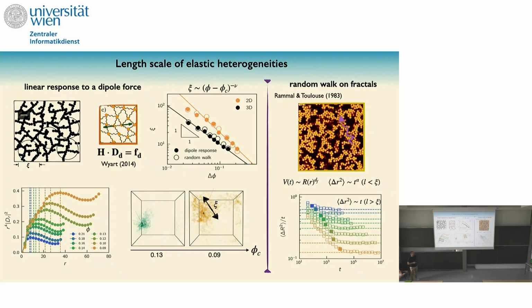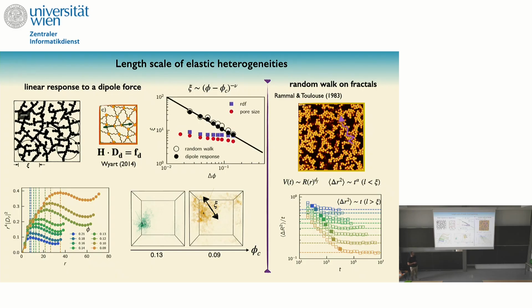Again, you might argue, and people have measured many other length scales, that maybe the important length scale is the size of the pores in my system. Maybe the important length scale is the one that comes from the radial distribution function when the system crosses over from something that is fractal to something that is not fractal. You can measure all these length scales, and you see that they do not follow what you would expect in order to get the right scaling for your modulus.